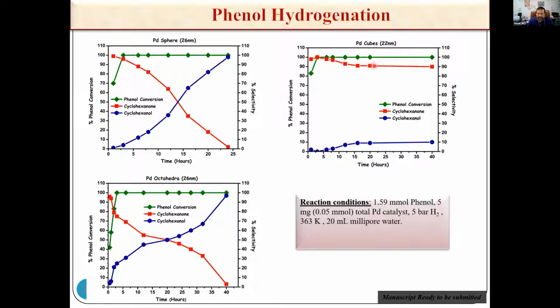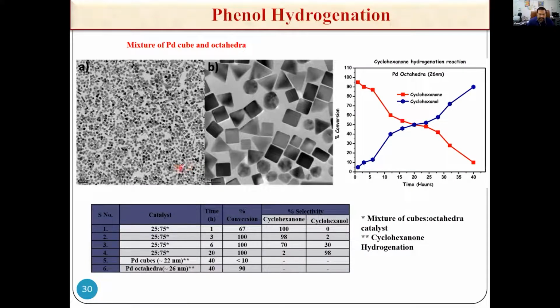So the difference is basically palladium cube carries only the 100 plane, whereas sphere and octahedra carry 111 planes. And we carried out a reaction where we try to mimic the spheres, where we mix palladium cube and octahedra in the same proportion that we see in the Wulff reconstruction, 25% palladium cube and 75% octahedra. And then when we run the reaction, you see that with extended period of time, it actually goes to cyclohexanol. Whereas on a palladium cube, if you try to do a hydrogenation of cyclohexanone, you don't see any conversion happening, because 100 is not really active for cyclohexanone to cyclohexanol conversion.